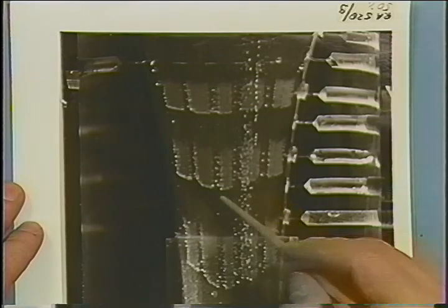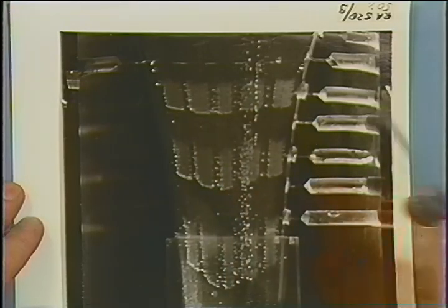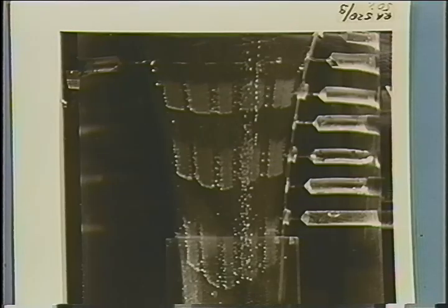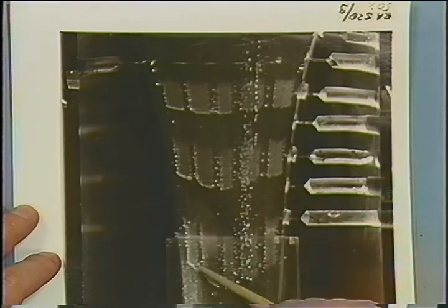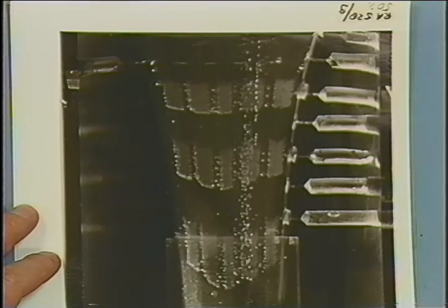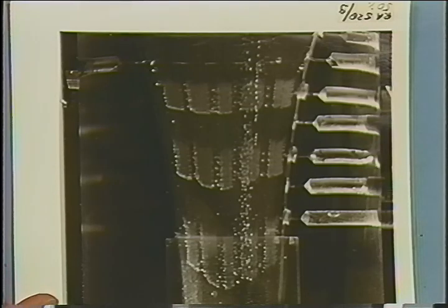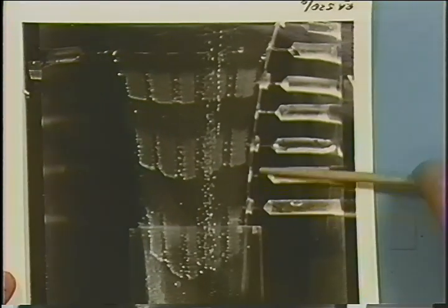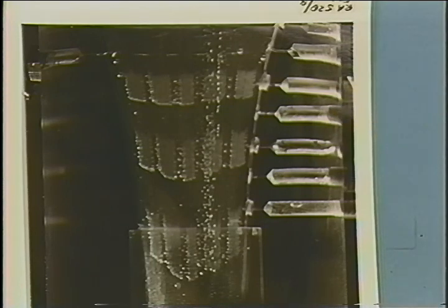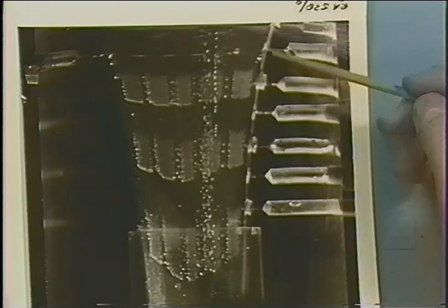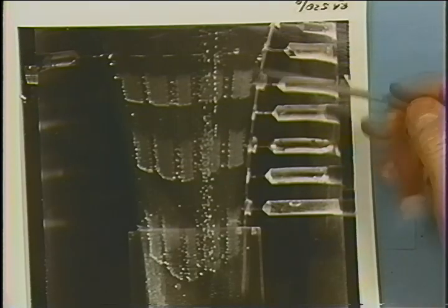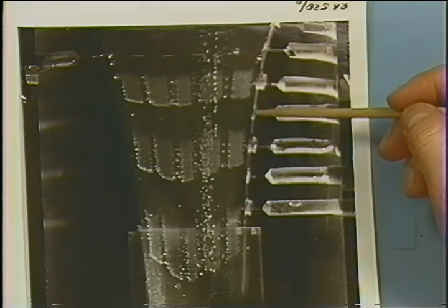But you also can see that the flow in the center is not perfectly flat. It's not just plug flow. There is still some shearing motion, and there is an acceleration. So in that sense, you immediately see plug flow is not being reached, and there's certainly shear in our liquid. And then we measured the pressure distribution on the side, which in some cases was determined by the lubricant liquid which we entered on the side. So it's somewhat tricky.